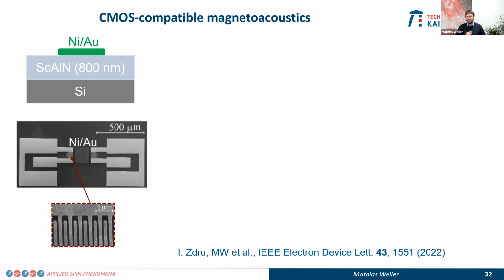So one further thing to look at towards potential applications of this is making it CMOS compatible. To do that, in collaboration with the IMT in Bucharest, we looked at samples where they deposited a nickel film with a gold capping layer on top of a scandium aluminum nitride piezoelectric layer, and everything is made on a standard silicon wafer. Okay, so it's thin film technology on silicon, so it's CMOS compatible.